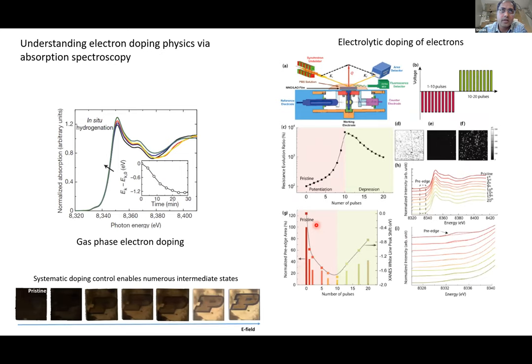And so we expanded from hydrogen to lithium. The figure you see here is actually lithium introduction. The physics is very similar. What we found was that when we added lithium or sodium, the phase transition was very, very similar. The strain is different. For lithium, for example, the ionic radius is larger than the proton, so you can have a larger strain when you introduce lithium versus protons. Similarly for sodium.